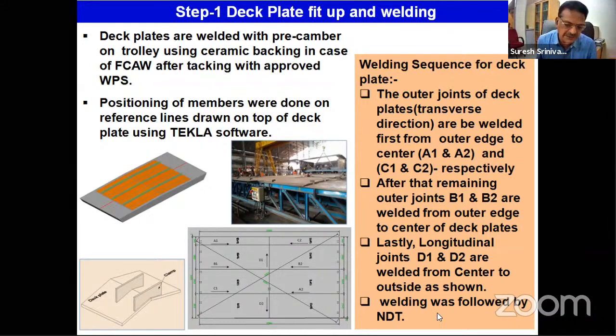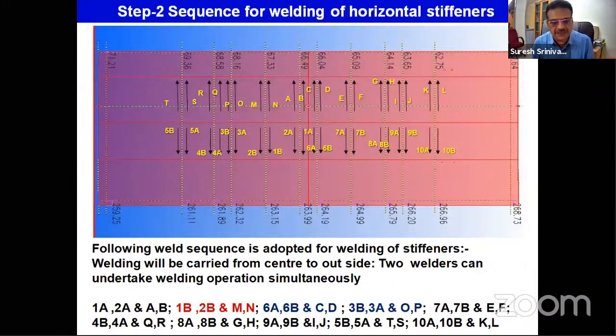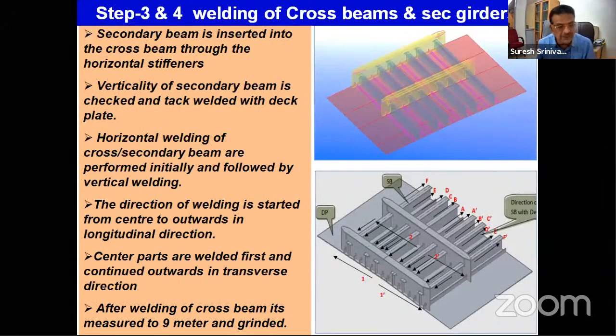So you can see the diagonals were being monitored after every stage of welding. And sometimes we use ceramic backing so that you need not turn the plate, because turning the assembly is a big job at the site, especially because we are handicapped with the lifting capacity. So here, we determined the welding sequence, welding direction, the welding order, everything was decided initially, and then we applied it on the mock-up. When everything was tested, we applied it on the actual structures. We applied sometimes 2 welders, 4 welders, according to the availability.